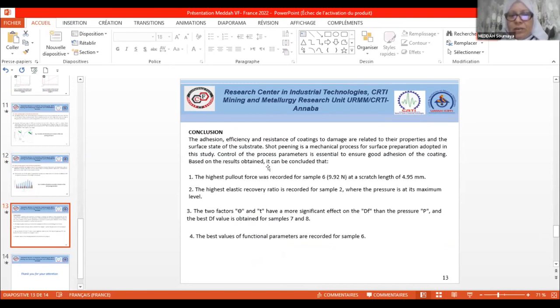Based on the results obtained, it can be concluded that the highest pull-out force was recorded for sample number 6 at the scratch length of 4.95 millimeters. And the highest elastic recovery ratio is recorded for sample number 2, where the pressure is at its maximum level. The two factors theta and T have a more significant effect on the fractal dimension than the pressure. And the best fractal dimension value is obtained for samples 7 and 8. And the best values of functional parameters are recorded for sample number 6.